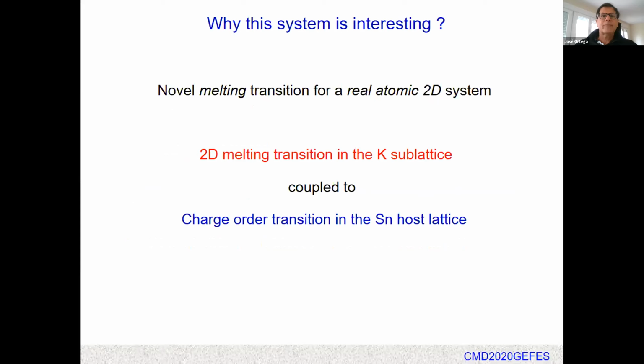So first, let me say why this system is interesting. Well, probably there are several reasons, but let me just point out one, which is that this system displays a novel melting transition for a real atomic system, two-dimensional. And this we can study using STM, STS, and DFT. In particular, in this system, we have a two-dimensional melting transition in the potassium sublattice, which is coupled to a charge order transition in the tin host lattice.